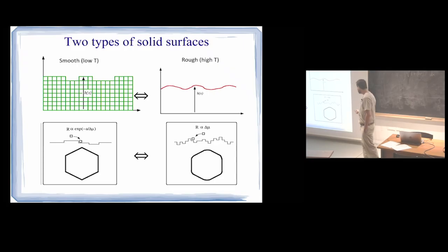Okay? And this is not well known, but it's a very, very real situation. And the problem is typically you cannot make pictures of these situations. Most rough interfaces occur between a solid and a liquid, and you cannot image that very well. Or they can occur at a metal interface close to the triple point, where the vapor pressure is huge and you don't want to make experiments at 1200 Kelvin. Okay? So that's why they're not well documented experimentally.